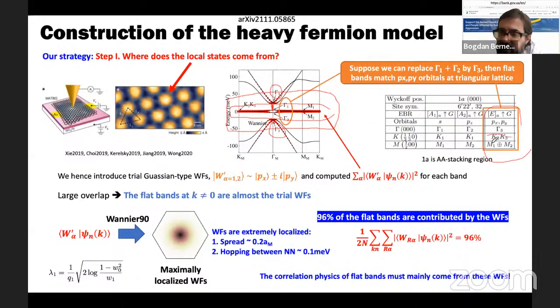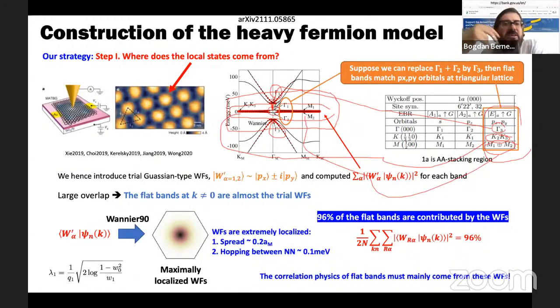So you see, the atomic limit of px, py orbitals on the triangular lattice has this representation at the K point, has the M1, M2 representation at the M point, and has the gamma 3 representation at the gamma point. So basically the culprit were these gamma 1, gamma 2 representations, which are some crystallographic representations that differ by the eigenvalue of C2x, doesn't really matter, they just didn't fit in an atomic limit. But now if I borrow some of the upper representations, I can build an atomic insulator, or an atomic band, exactly on the triangular lattice. So let's go and do that.